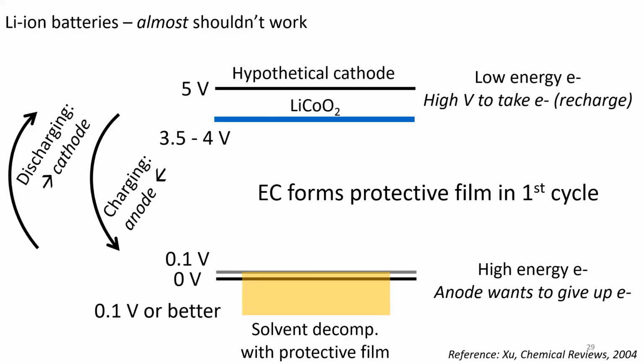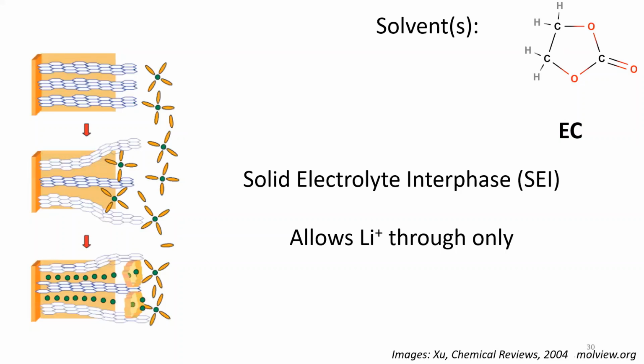Okay? But ethylene carbonate, if we have it in our electrolyte solution, a little bit of it breaks down on the anode during the first cycle of the battery and forms a protective film. This protective film is a little bit different than the one on aluminum. It has atomic sized holes in it to let lithium ions move in and out so the battery can be discharged and recharged, but the holes are small enough that they prevent any other solvent molecules or anions from getting in and touching the graphite.